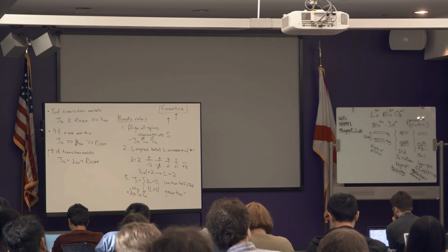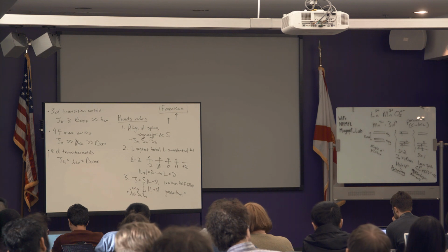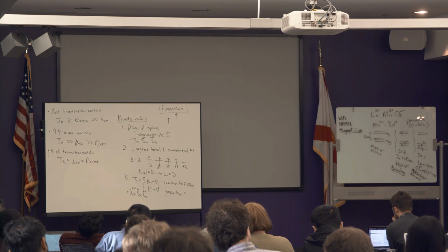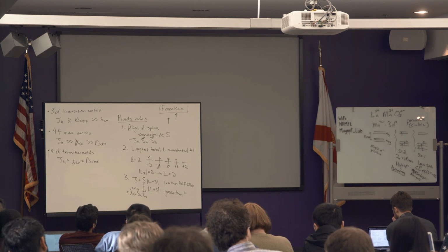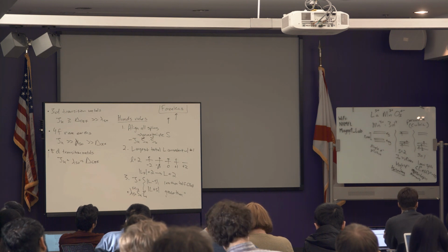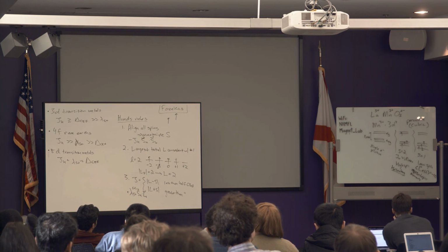If you do exactly that same picture for L equals 3 for f electrons, you find that your L is 5 because you have a minus 3 and a minus 2. And your spin orbit then couples these together to get a J equals 4 term. So if my praseodymium atoms were in free space, then I would have 9 degenerate levels.